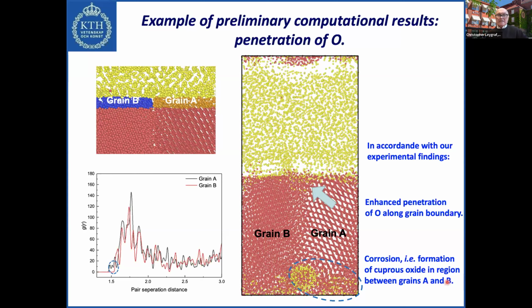So this is maybe quite advanced, and I should emphasize again preliminary, but the interesting thing is that it seems to show the same type of phenomena with internal corrosion as a result of cuprous oxide formation along the grain boundaries. So we are quite clear that there is something quite enhanced occurring deep inside the copper material at 60 degrees.